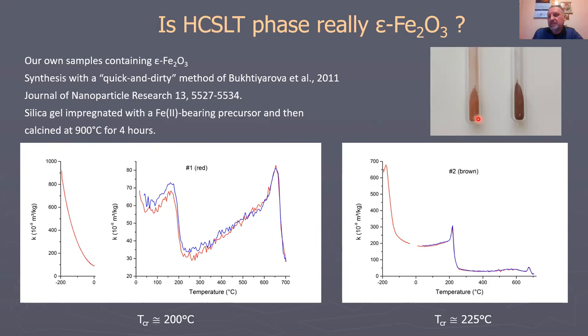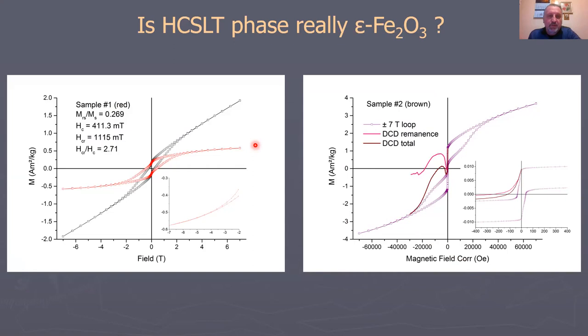And there you can see that depending on the gel used, the samples differ in color. That one contains obviously more hematite, as you can see in the thermomagnetic curve as well, and that one contains obviously less hematite. We also saw that the transition temperature of the epsilon phase is a bit different in these two cases. On the other hand, the hysteresis properties at room temperature have shown something really very strange, particularly for this brown sample. For the red sample, it's more or less similar to what we would expect in some ceramics at least.